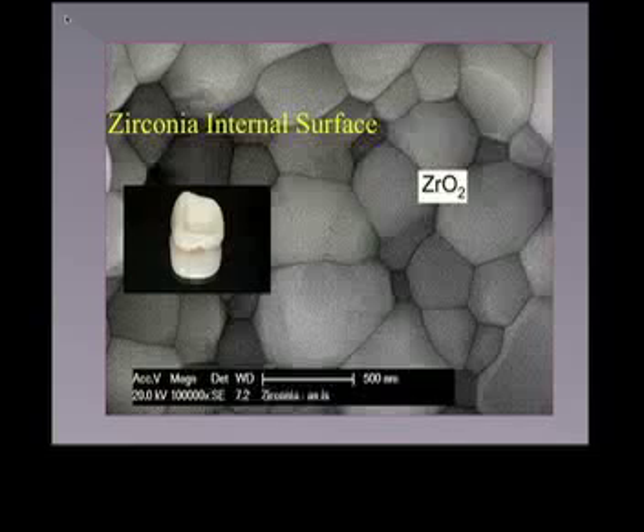And so when we talk about zirconia, it's crystalline, as you can see in morphology, and doesn't contain silica. And so it renders hydrofluoric acid and silane ineffective. It just doesn't do anything, hydrofluoric acid and silane has no effect on zirconia.